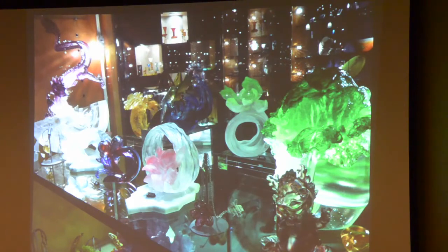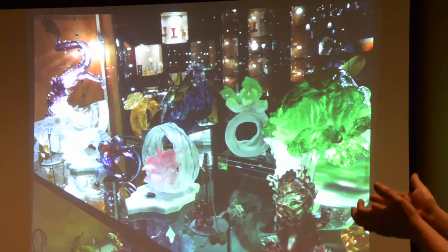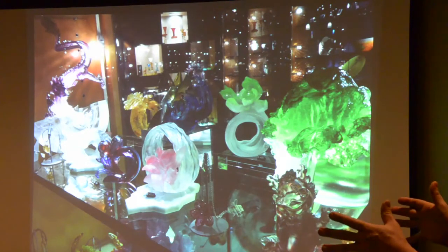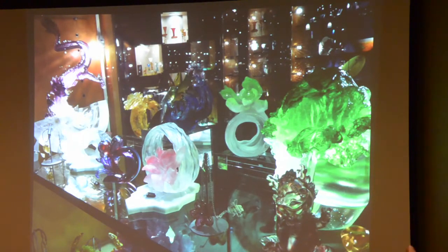And then they're going to make sort of a cylinder of plaster flint mix around that. Burn that out, and then they'll put glass. You can even load your chunks of glass on top of this plaster cylinder, put it in the oven for days, let that glass melt down into place, and cool slowly, annealing in the process. And after it's cold, you kind of chisel out gently and carefully all that refractory around it, and you've got a neat dragon. The dragon will always have a rough matte surface on it, so then you got to do a lot of polishing if you want to get it to a smooth surface again.